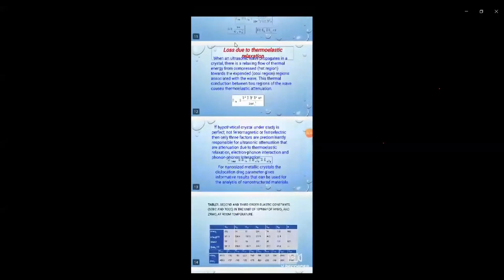Attenuation due to the thermoelastic relaxation mechanism. The equilibrium distribution of the thermal phonons in a solid is disturbed by the passage of ultrasound waves, and the re-establishment of the equilibrium is maintained by the relaxation process. The process produces entropy, with the result of absorption loss due to thermoelastic relaxation. When the ultrasonic wave propagates in the crystal, there is a relaxation flow of thermal energy from the compressed towards the expanded regions associated with the wave. The thermal conduction between two regions of the wave causes thermoelastic attenuation.